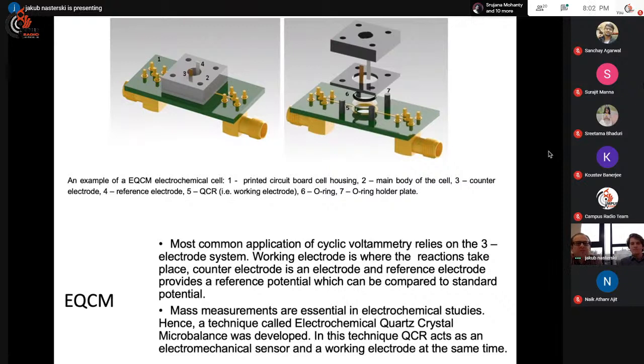Yeah, so when you know the zero, you can measure the potential of your battery, and then you know that this battery gives 1.5 volt or 3 volts or 9 volts. And in the technique called EQCM, crystal acts as an electromechanical sensor, which allows us to measure mass and viscosity, and it's also a working electrode. So you basically do all your reactions on the crystal and measure mass and viscosity changes occurring there.